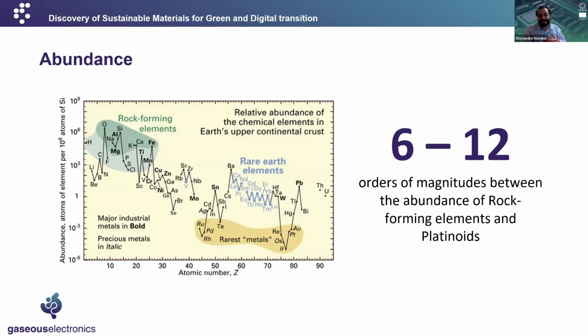which does not mean that it corresponds exactly to the reserves or to the production. This is slightly different, but anyway, we understand that we have quite a lot of silicon available, iron, magnesium, titanium, manganese. This is what we call rock-forming elements. However, iridium, rhenium, osmium, platinum are extremely rare. Just to give you an example, we produce approximately 500 to 1,000 kilograms of osmium per year for the whole Earth. So this is not something for the mass market.